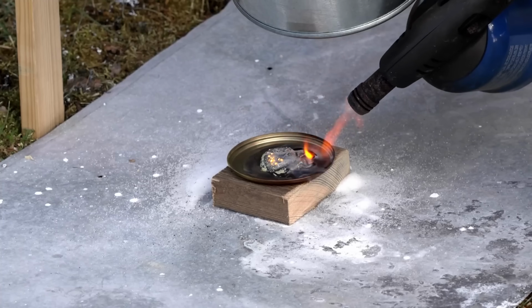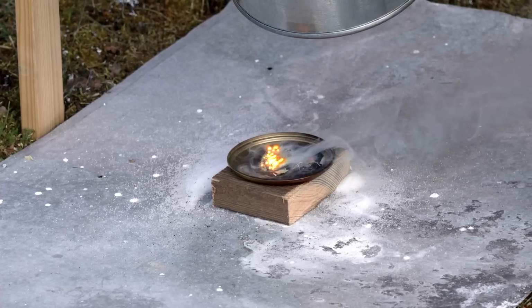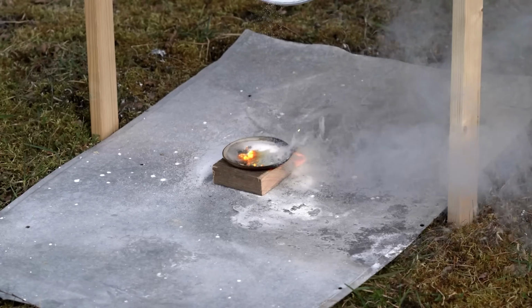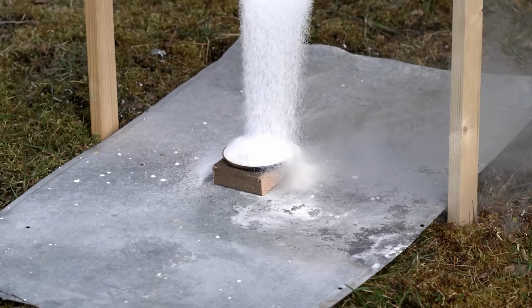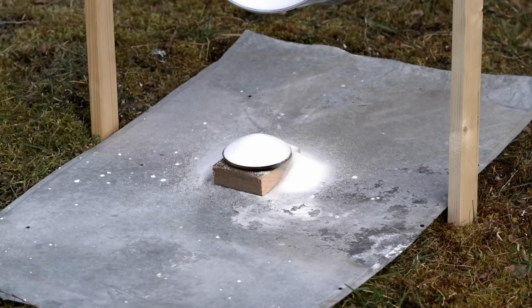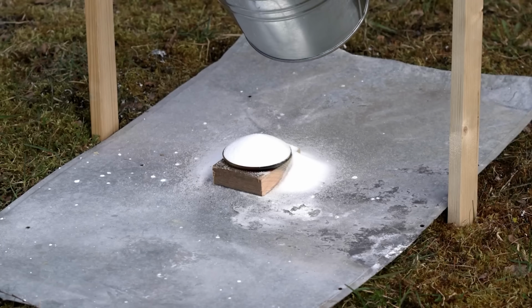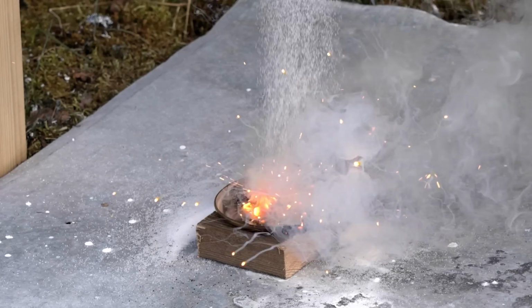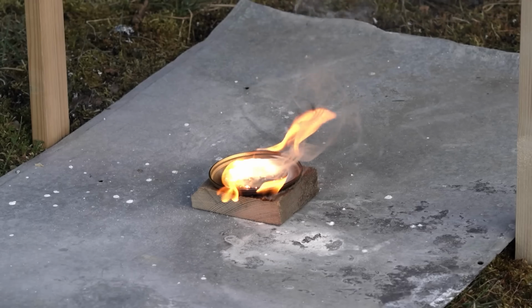The first metal I tried to extinguish was sodium, just like the previous test. As you can see, the salt coped with the fire perfectly well. Actually, so did the sand. Sodium splattered a little bit, most likely due to the fact that the salt wasn't dry. Next, I did the experiment with burning lithium.